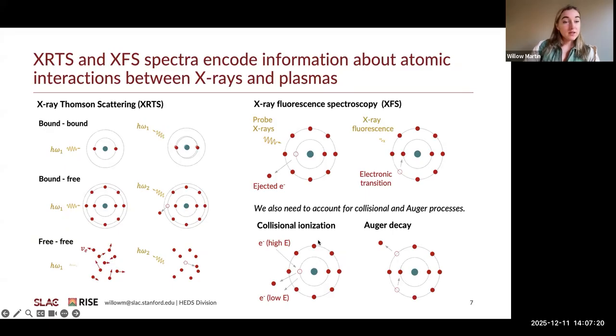Our more challenging diagnostics that we were aiming to optimize were focused on measuring the temperature and density of underlying material heated to high energy density states. There's a dearth of temperature diagnostics that are applicable at high energy density, which kind of motivated us to focus on these diagnostics in the first phase of our campaign.